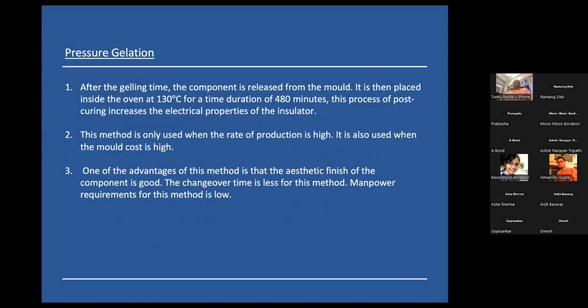Now after the gelling process, the component is released from the mold. Then it has to undergo curing again in the oven. The time duration for this is around 480 minutes. The main reason is that the curing process is important because it improves the electrical properties of the insulator.